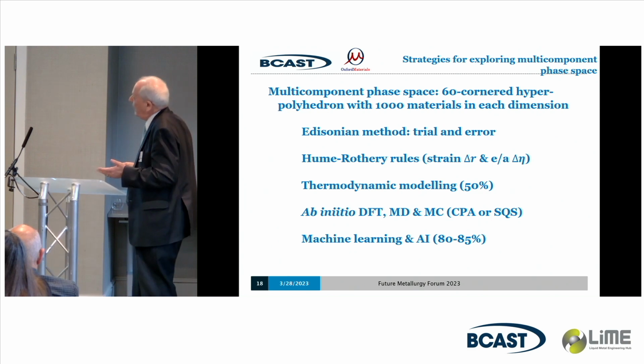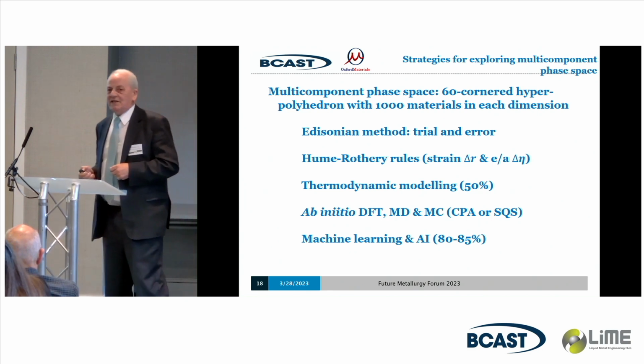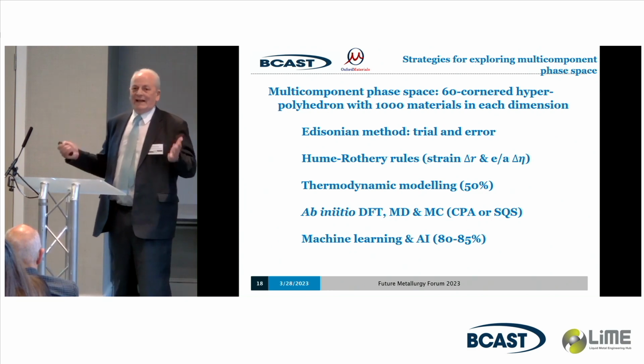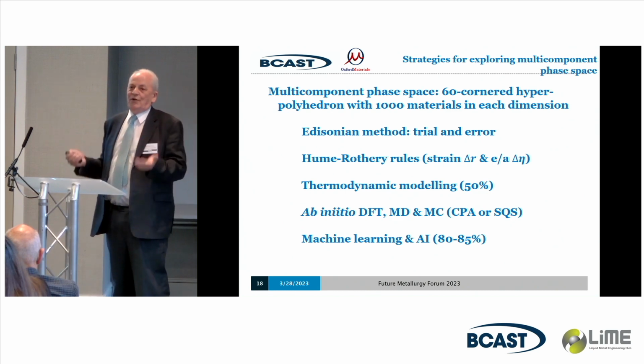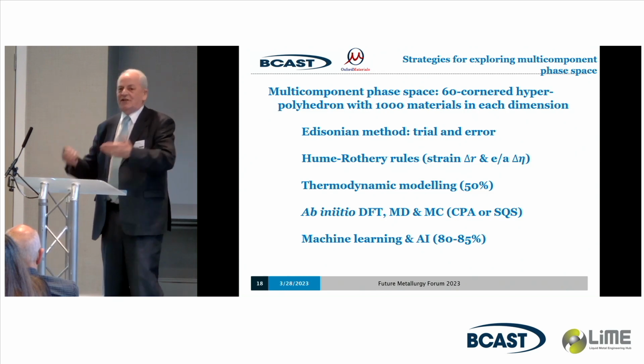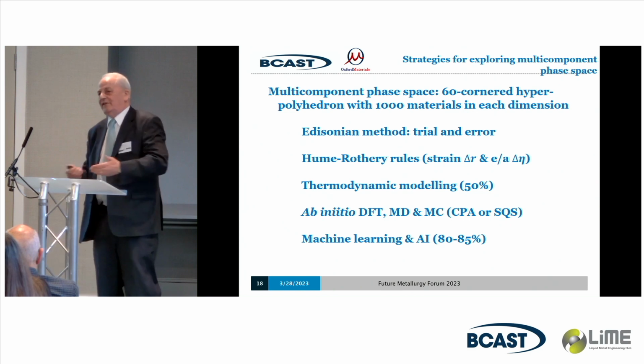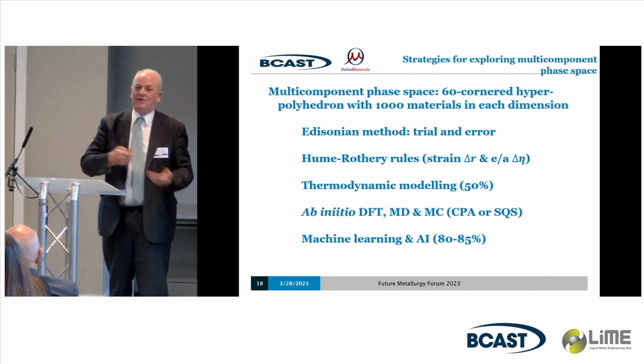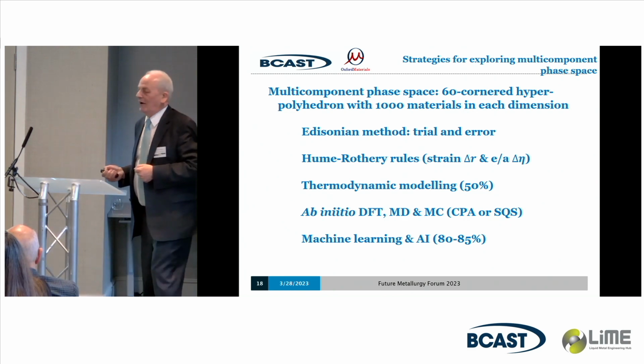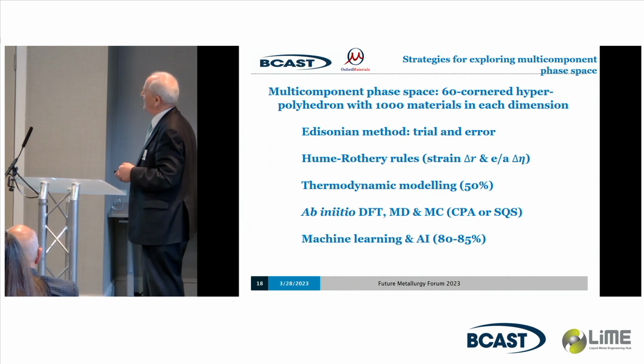So there's been loads of papers published on it, which haven't really got much better than saying, well, the Hume-Rothery rules work roughly. Thermodynamic modelers came along and said, well, we can do it all by thermodynamic modeling. They can't. The parameters you need to do thermodynamic modeling, anything beyond a binary or ternary system, are so complicated, unless you make the material in the first place, you don't have the parameters to be able to predict it. So you can't predict it before you've made the material, which is what people are hoping to do, as a way of charting this enormous region.